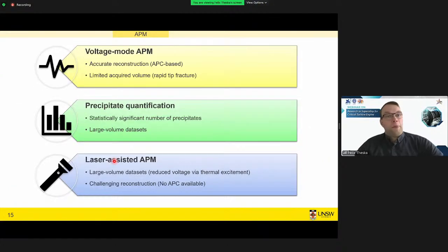Okay, so that's quite nice for voltage Atomprobe microscopy, but the problem is here we usually need quite a high voltage, which means there's a high risk of fracturing of our sample. And when the tip fractures, the experiment is over, and that's all the data we get. We need to make a new sample. If we want to quantify these precipitates, we need relatively large volumes so we get some good particle statistics.